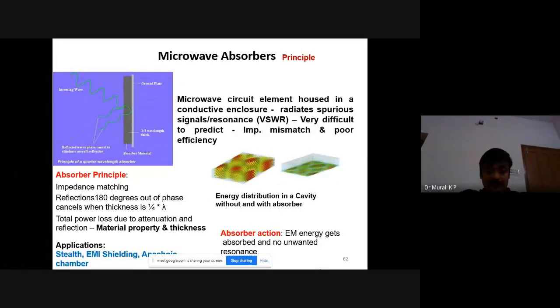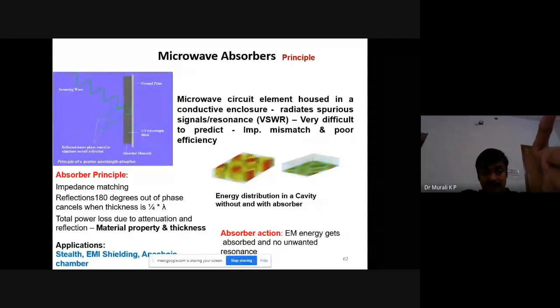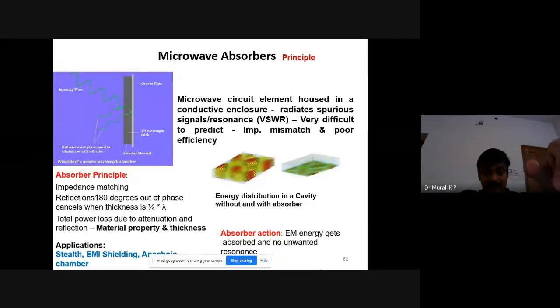Electromagnetic wave comes and impinges on the first air or the medium, the dielectric or the material which is given in black, and it passes depending on the impedance match. It goes into the material, and there is a back plate which is a ground plate, which is metal, and from there it gets reflected. So there are several mechanisms happening in this. Either the absorbing material which is given in black, if it is highly lossy, like high electrical and magnetic loss material, it will absorb that. The material will absorb it, and the electromagnetic wave will get attenuated while it is passing through because of the loss.